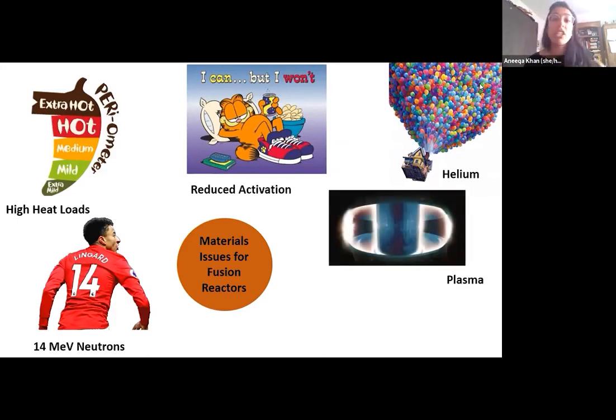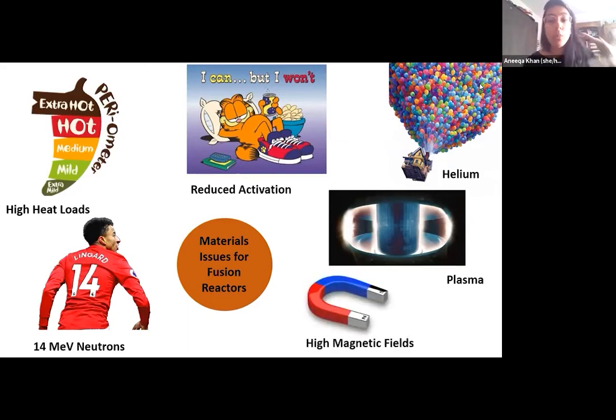And then just more generally, the interactions of the plasma with the materials, what influence that has. And then, as I mentioned before, the high magnetic field. So what materials can we use to generate those high magnetic fields to control and contain that plasma? And also, how does that magnetic field affect the other materials we're using in the reactor as well? That's another area of research. So in ITER, for example, we're talking about magnetic fields of around 13 Tesla. Now, if you compare that to an MRI scanner in the hospital, which is 1.5 Tesla, which is already considered very, very high, a really significant magnetic field. So the influence of that, again, is another really key area